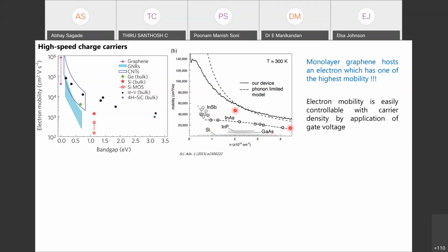But compared to all these materials, graphene shows a mobility which is shown here by a solid line. As you can see here, at a carrier density of 1 times 10 to the power 12 per centimeter square, the mobility in graphene is 100,000 centimeters square per volt second.